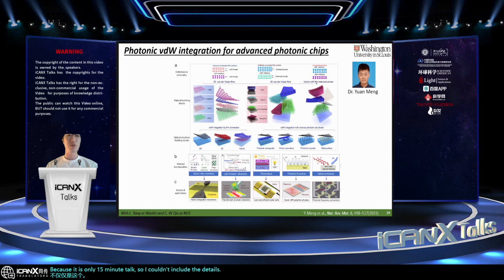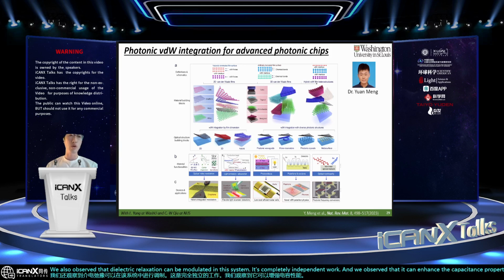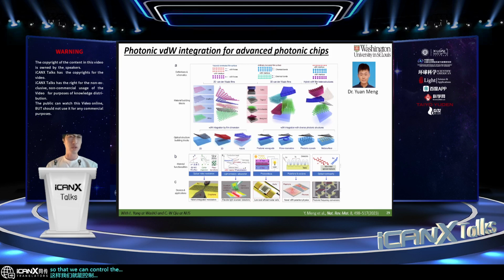And we observed many different properties. For example, we also observe that the dielectric relaxation can be modulated in this system. It's completely independent work, and we observe that it can enhance the capacitance property, so that we can include more charge, so that we can control the material's density of states. When we incorporate it into a photonic device, we also observe a more energy-efficient device. Okay.